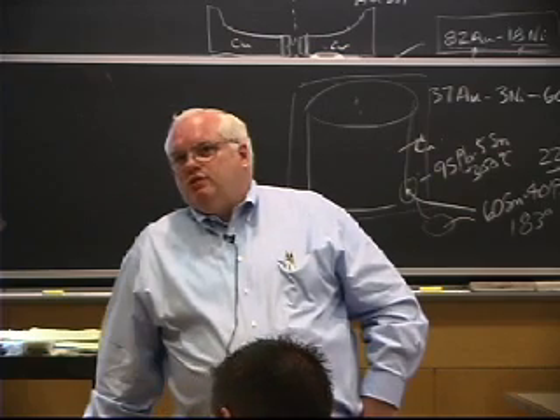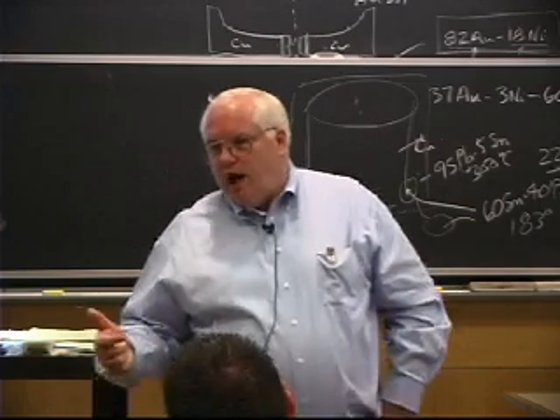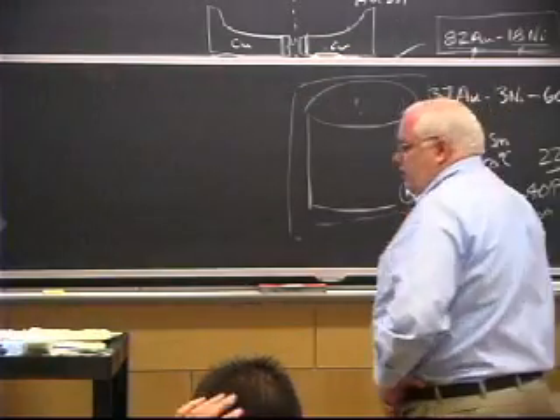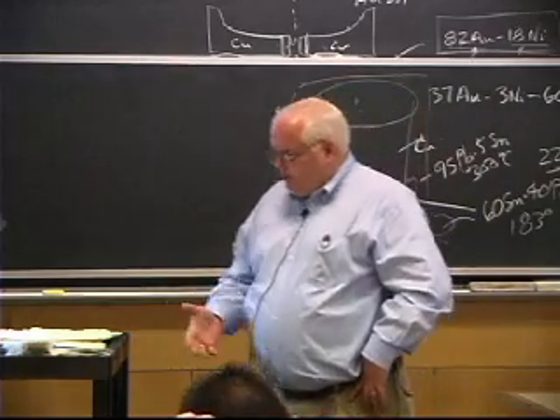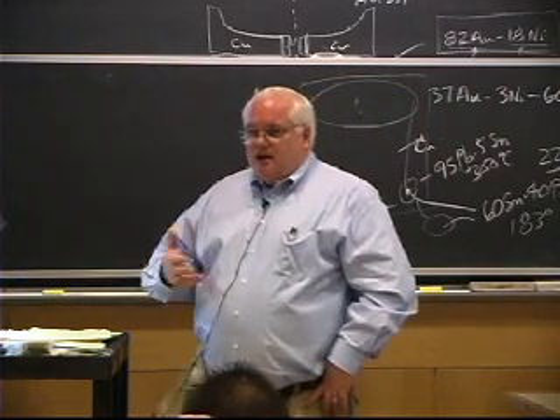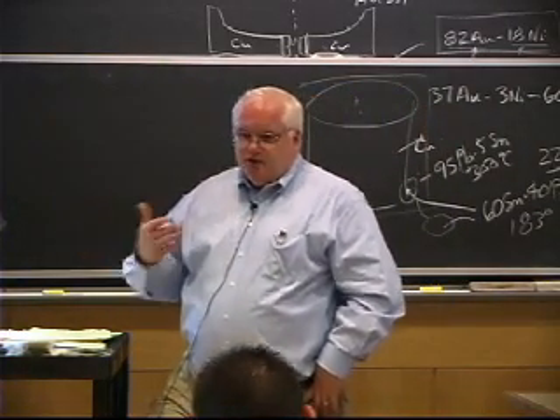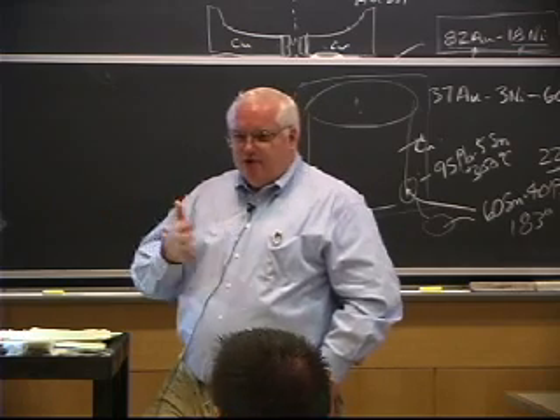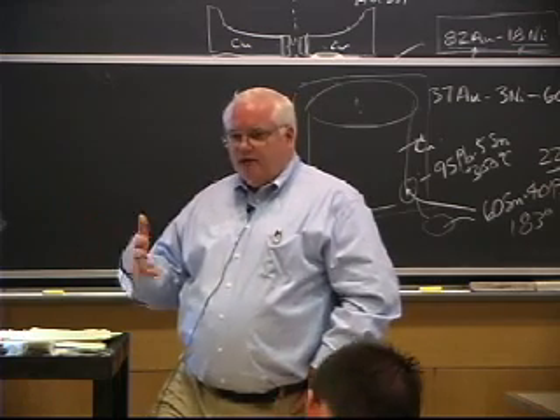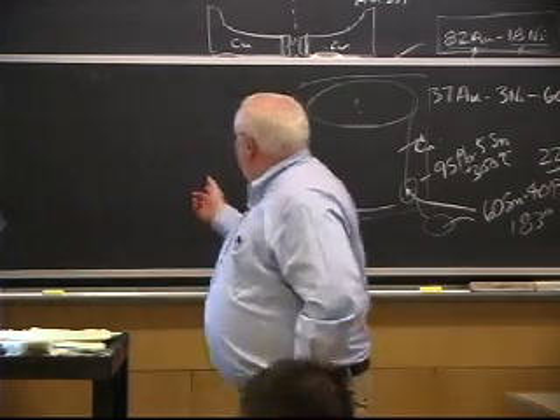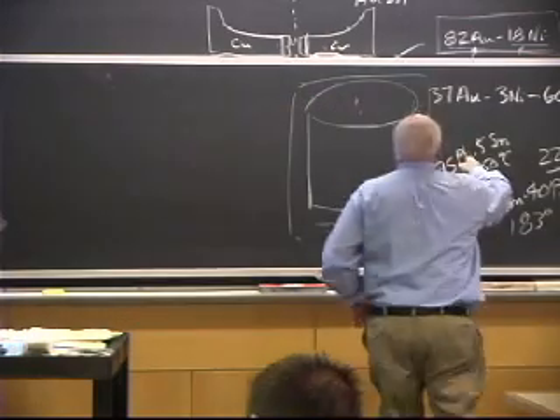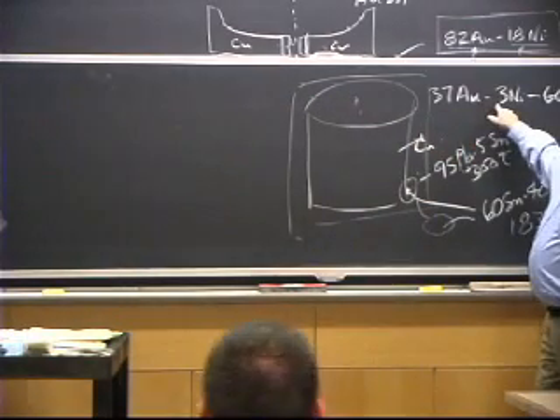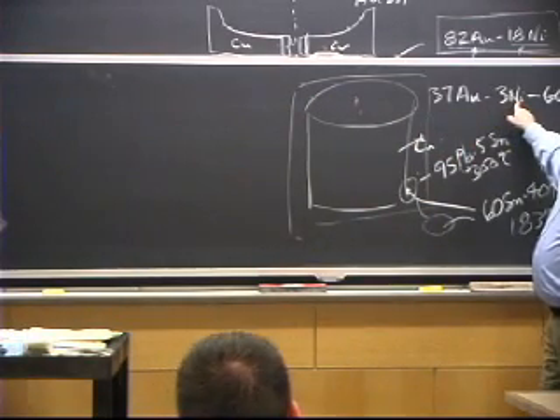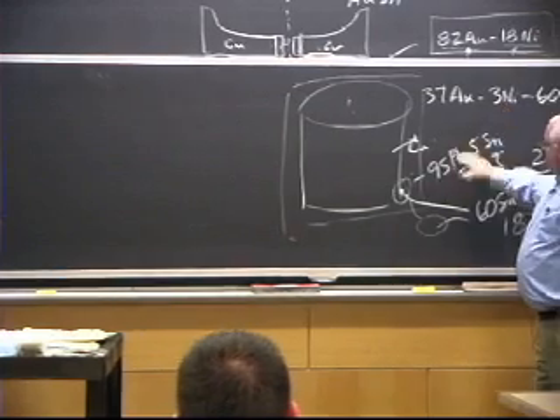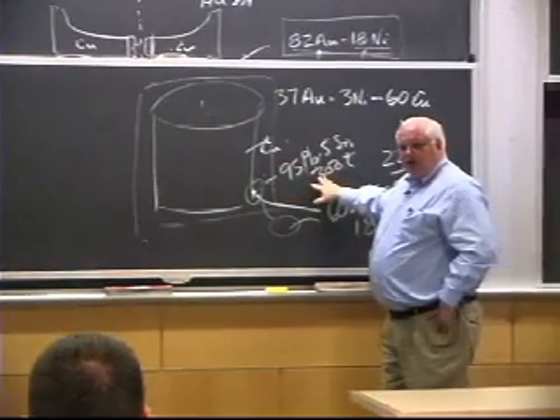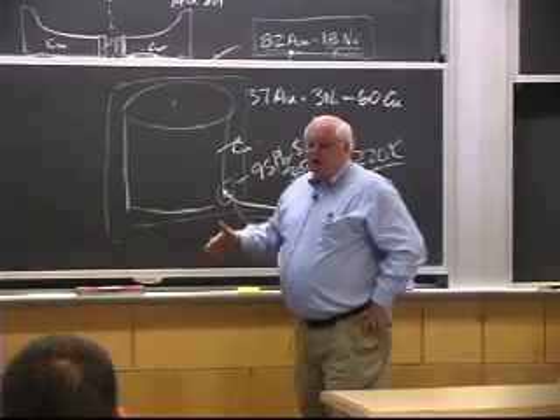In many cases, you can find a braze alloy. I always thought that there were nickel boron braze alloys for these jet engines, and someone just left it in the furnace too long. It's always been my theory, and they found out they ended up with a better joint by leaving it in the furnace too long. In this case, these guys thought they were going to a different braze alloy, and in fact, they ended up with a TLP joint. Okay. In the case of this, they're using a regular solder alloy, and they ended up with a TLP joint.